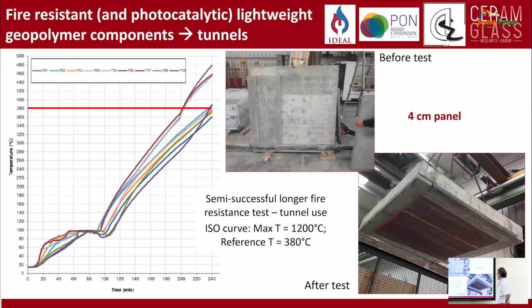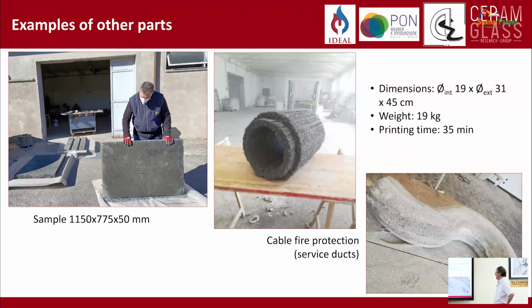So a semi-successful test, but you can see that due to the refractory characteristics of the geopolymer, bear in mind that this geopolymer was not fired; it was just printed, and then it was directly exposed to the high temperature, and there are no significant cracks. The material remains intact. And this is the major advantage of geopolymers with respect to, for instance, cement.